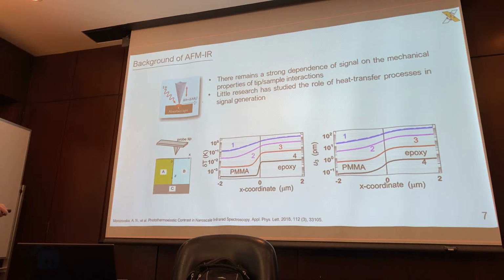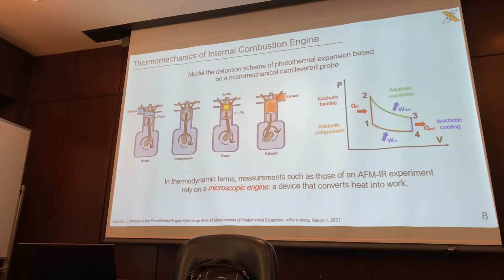You'll notice that the change in temperature between PMMA and epoxy is quite sharp, but the actual deflection is far more gradual. So this tells us that this process is not very efficient at all. We're losing a great deal of heat. And so if we begin to model this as an engine, which in terms of efficiency many people have done, I wanted to go over, well, what is an engine? The definition of an engine is something that you put in energy to get work out of, as I mentioned before. And so if we try to model the photothermal expansion based on a micromechanical cantilever and compare the cantilever to a piston in a combustion engine, in this case we have 4 different processes.